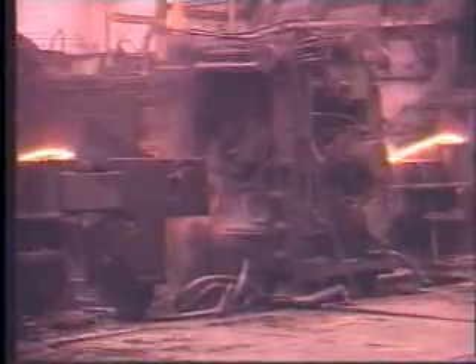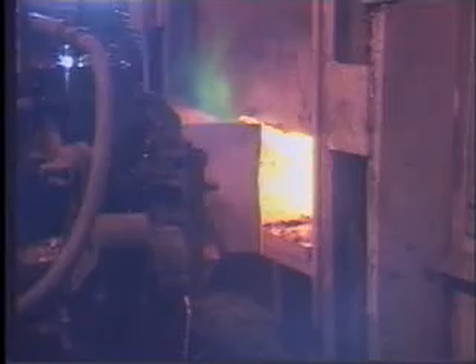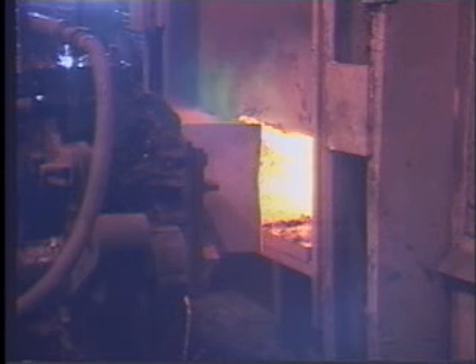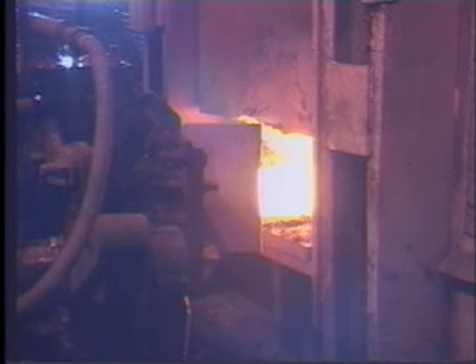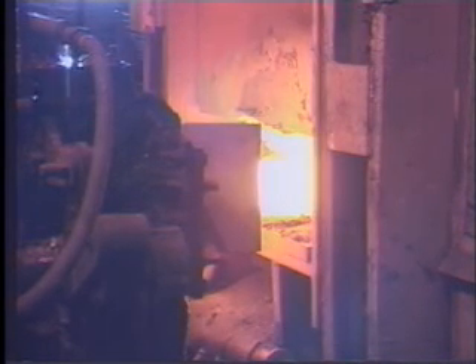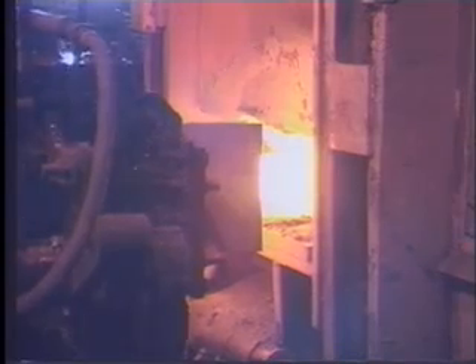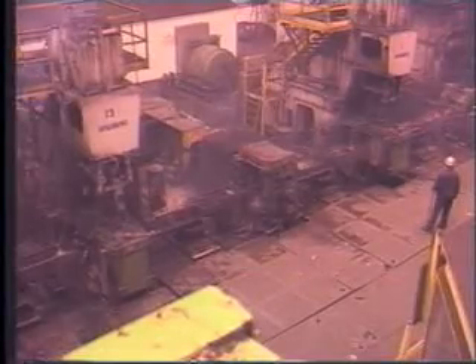A rod mill consists of 25 sets of rolls, which reduce the billets to their final round shape. Sections as small as 7/32 can be obtained on this mill. Prior to rod rolling, the billets are heated to a uniform temperature, approximately 2,000 degrees Fahrenheit. The heated billet exits the furnace and proceeds through the individual mill stands. As the section is reduced, the speed of the material increases. 7/32 inch rod will achieve speeds in excess of 200 miles per hour at the end of the rod mill.